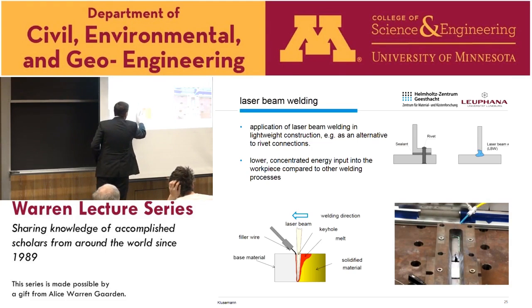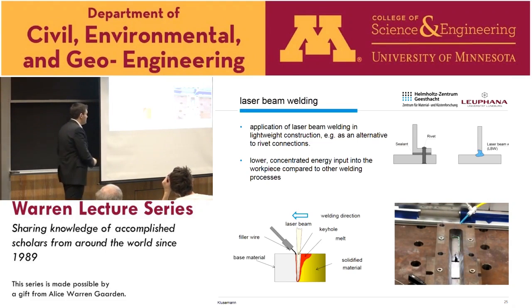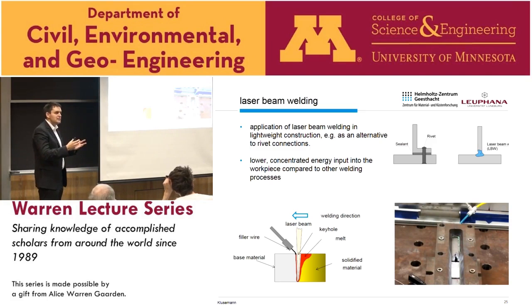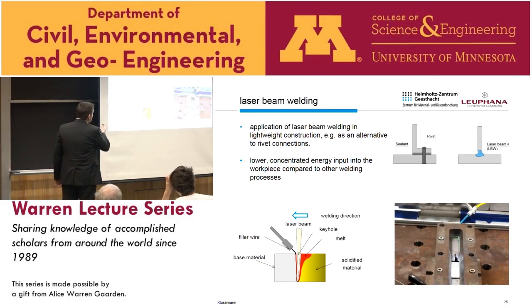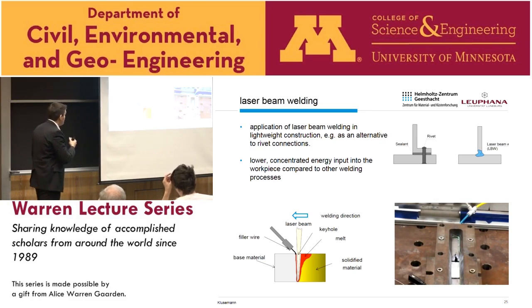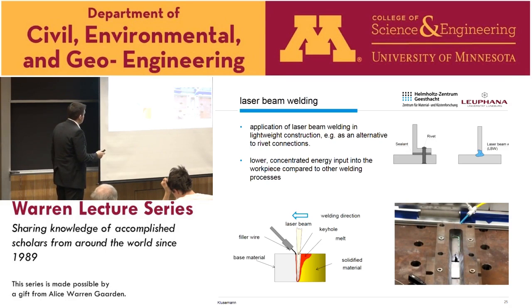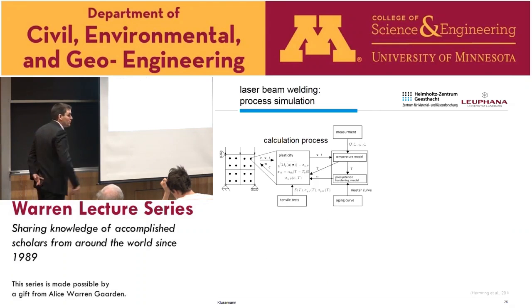So we have 2 samples, a butt joint, and we have our laser running over that. Here's our laser beam, we have a kind of melting of our material, and then the material solidifies, and we have a connection between the two parts. So why is laser beam welding in general a nice technique? Well, it allows a lower and concentrated energy input into the workpiece compared to other welding processes. So you can do it very concentrated.